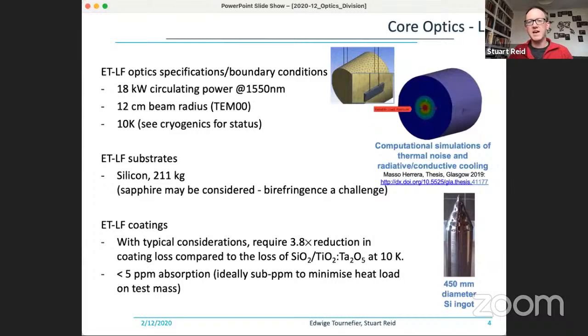Within the low frequency part of the Einstein telescope, we then operate at cryogenic temperature with much lower circulating laser power. So we're now down to 18 kilowatts instead of 3 megawatts. But we push the wavelength out to 1550 nanometers, which opens up the possibility of using silicon substrates for the test masses. Again, 12 centimeter beam radii and 10 Kelvin operation. But again, when we think about system integration, we need to check whether this temperature is achievable when we take into account the other cryogenic and suspension